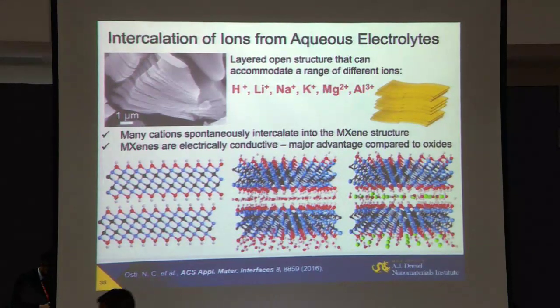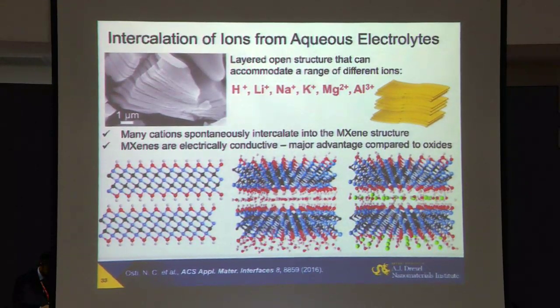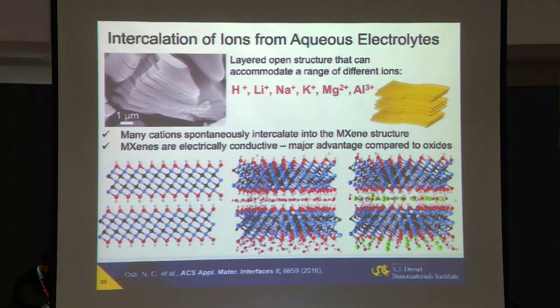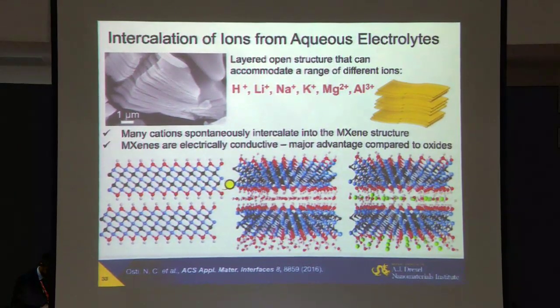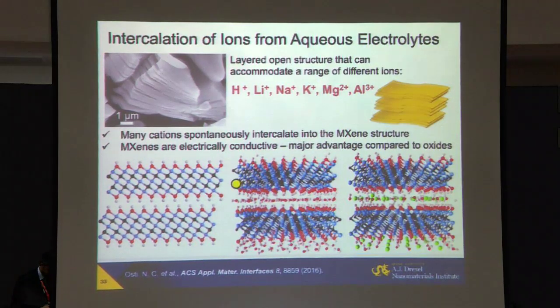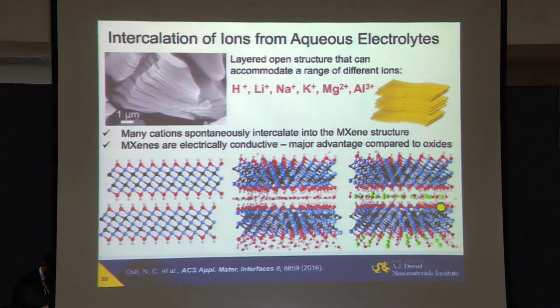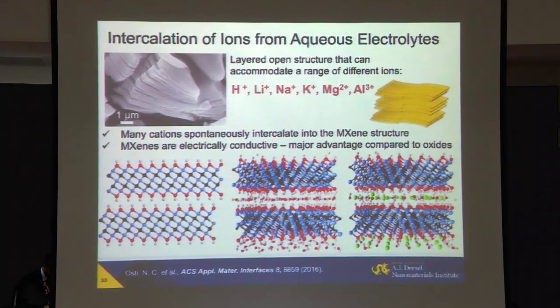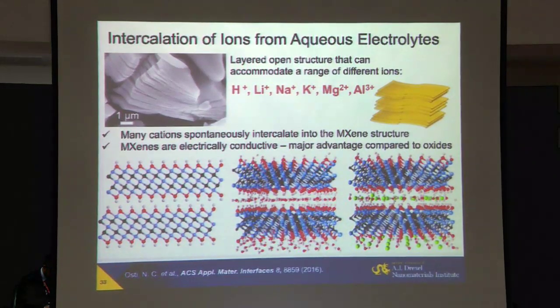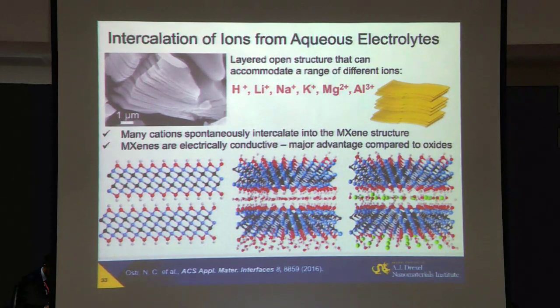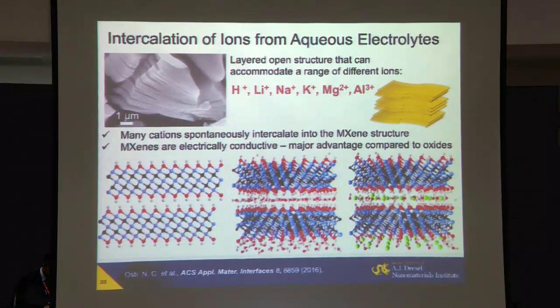Because what do you need to store energy? You need to be able to transfer electrons in a battery or pseudocapacitor, as we call these materials. I already mentioned the outer layer transition metal, which can change oxidation state as you apply potential if you bring ions to the surface. But this material can also transport electrons in the middle layer. Between the layers, here you have a model showing water molecules, and here water molecules with potassium ions, you can transport ions. So you have basically a material that has metallic conductivity, ionic conductivity, and is capable of changing oxidation state. That's exactly what you want from a good material for energy storage.